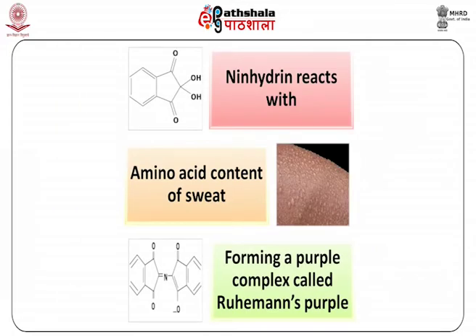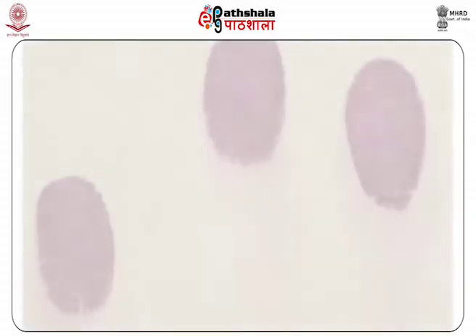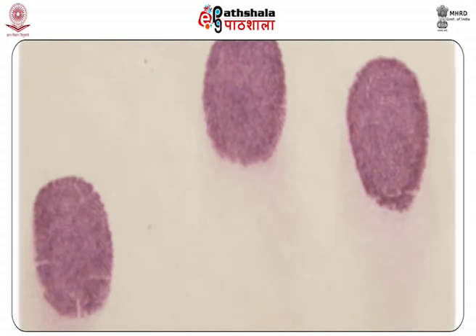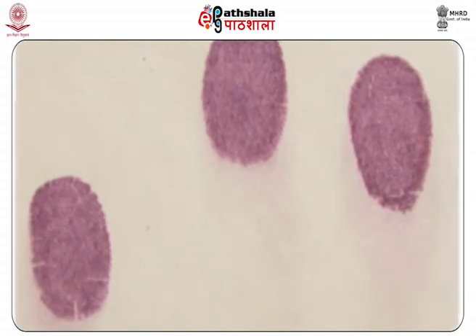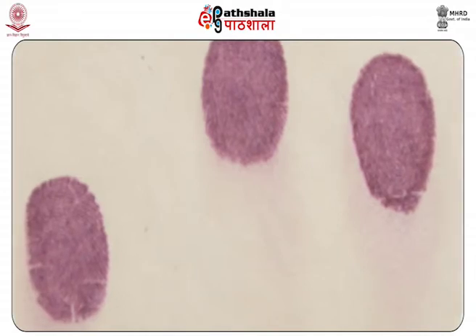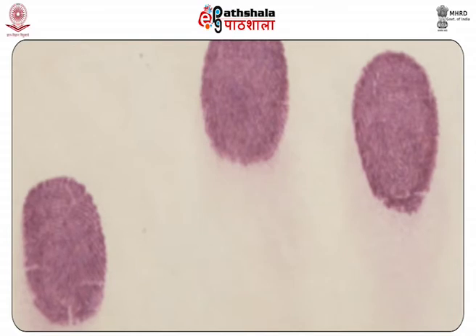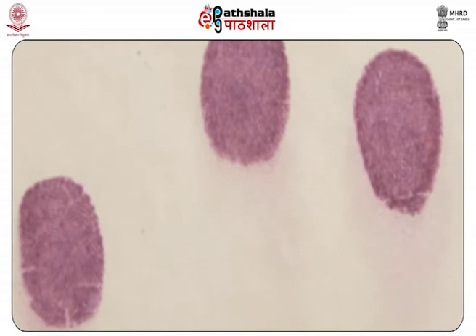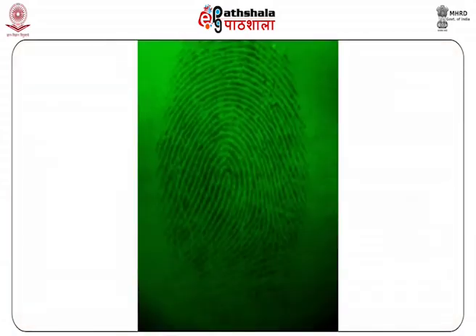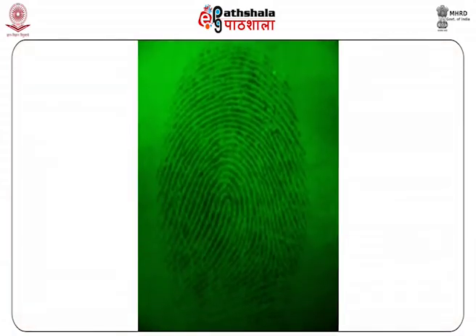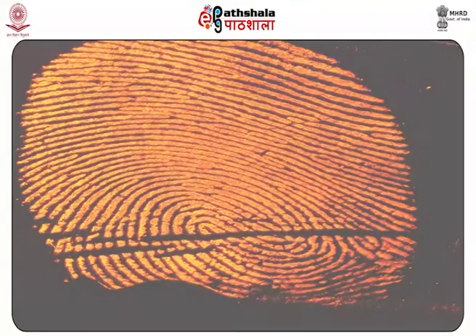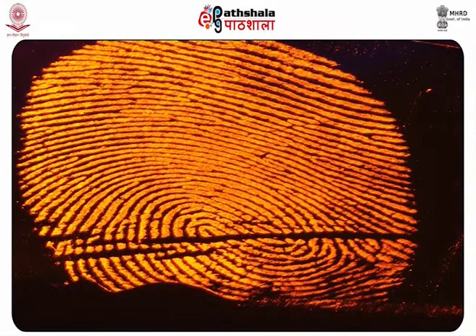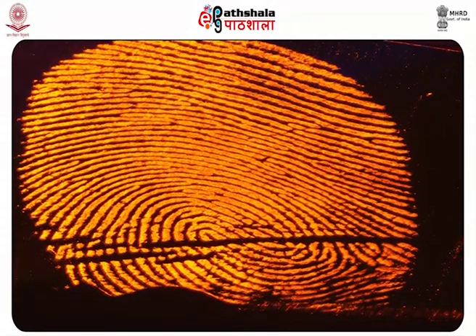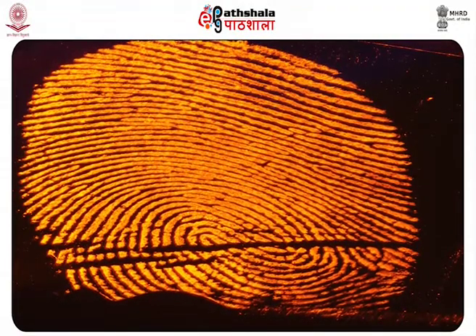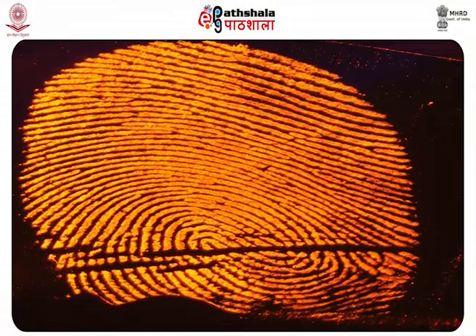Ninhydrin reacts with the amino acid content of sweat, forming a purple complex called Ruhemann's purple. However, the concentration of amino acids in sweat is quite low, as a result of which the developed prints do not show sharp contrast. To improve the clarity, prints are post-treated with salts of group 12 elements of the periodic table. This results in conversion of non-fluorescent Ruhemann's purple into a photoluminescent complex. The color of ninhydrin developed fingerprints changes to red or orange on post-treatment with zinc chloride or cadmium nitrate. Subsequent observation under an argon ion laser produces appreciable luminescence.